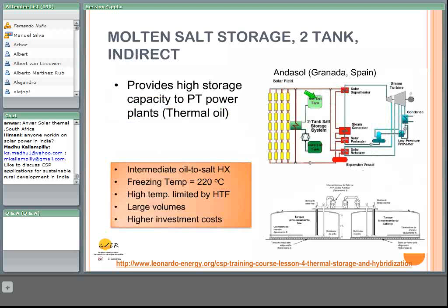The maximum flow rate is almost 1,000 kilograms per second, and as we can see here, the delta T between the cold tank and the hot tank is a little bit less than 100 degrees. The hot tank temperature is limited by the temperature of the heat transfer fluid of the solar field, and the cold tank temperature is limited by the melting point or the freezing point of the molten salt mixture. Again, here we can see the picture of this thermal storage at the Andasol plant.